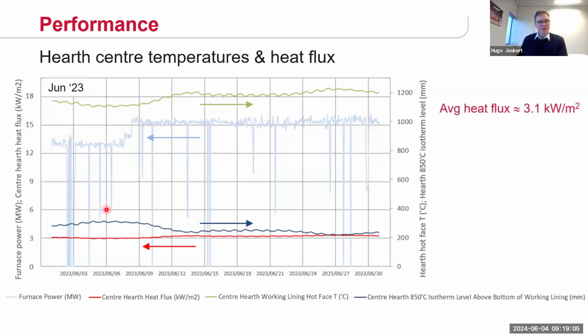If you look at the red line, it indicates the heat flux in the center of the hearth, and that was on average about 3.1 kilowatts per square meter, which is in line with what we estimated. The hot face temperature of the hearth is lower than what we anticipated, and we believe this is due to the deeper matte bath that we have inside of the furnace due to the lifting of those matte tapholes. It's because you're keeping your electrode tips further away from the hearth hot face.